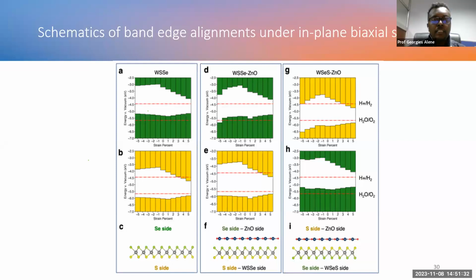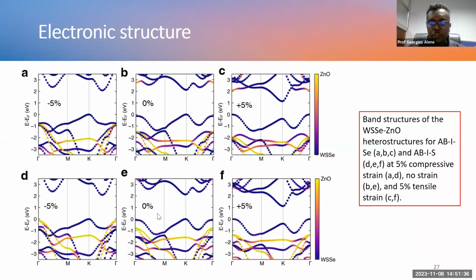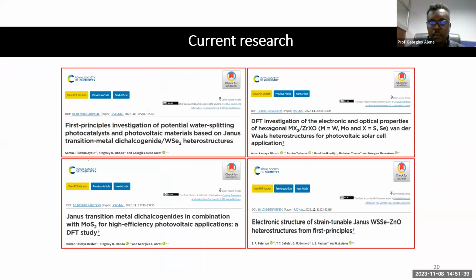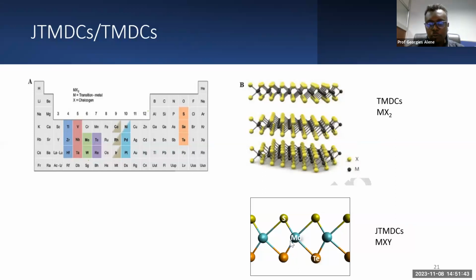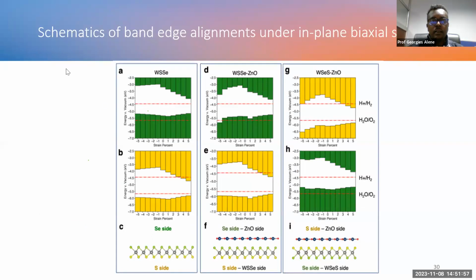You know, when we have the Janus transition metal dichalcogenide, I think I can show with another schematic here first. Here, for example, you have molybdenum in the center plane, and tellurium and sulfur. So you have two different sides: one is the sulfur side and the other is the tellurium side. The same is true for this heterostructure, WSSe. It has both a sulfur side and a Se side. So if you investigate the sulfur side for photocatalytic activity, that means the surface on which the photocatalytic reaction happens, then we say it is the S side. If it happens on the Se side, we say it is the Se side. That is the difference.